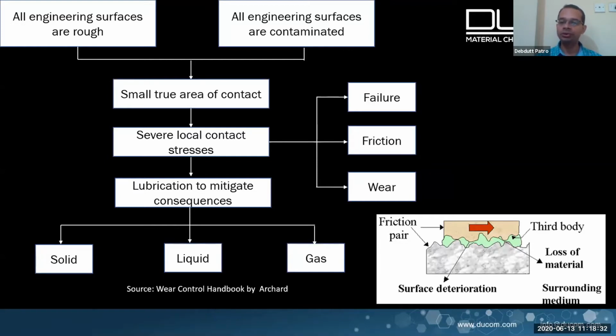Now, if we look closely at a schematic of what happens when these surfaces rub, and this is the image on the bottom right of this slide, you can see a top surface and a bottom surface. And if you zoom in really close, you see that there are asperities which are touching at certain points, and that is where you get a lot of high stresses and tendency for wear happening. In between these two bodies, there is an arrow which indicates a third body. So this third body could be a very important element in this entire study. The third body could be a solid, liquid, or a gas, which is introduced in order to prevent wear and friction.